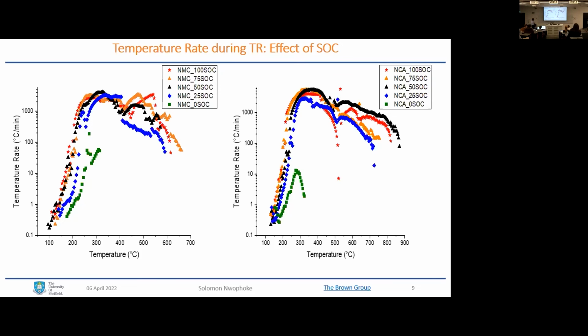For state of charge up to 50, you can observe that the rates are similar. It's just that at higher state of charge, it occurs a little bit earlier than at lower state of charge. And the same happened for the second sample, which is the NCA. You can see the 0 state of charge having a low heating rate, and the rest having a higher heating rate, but similar.